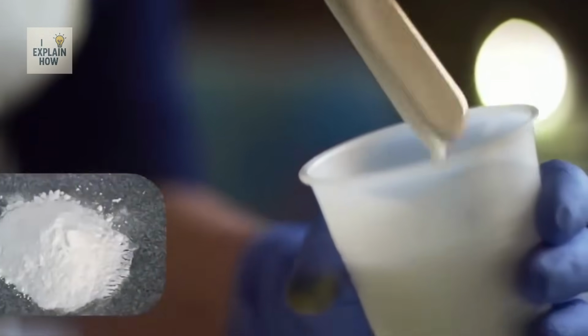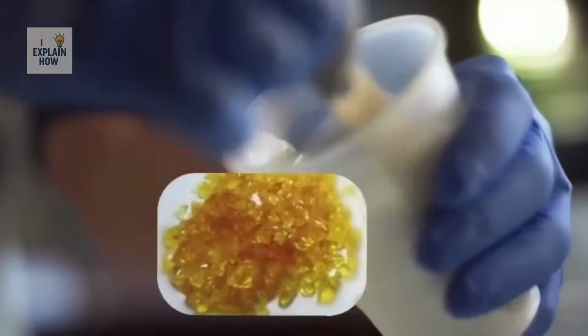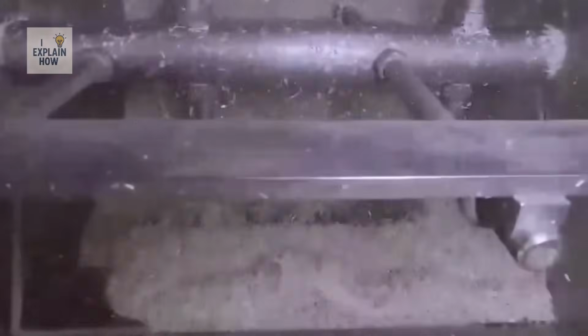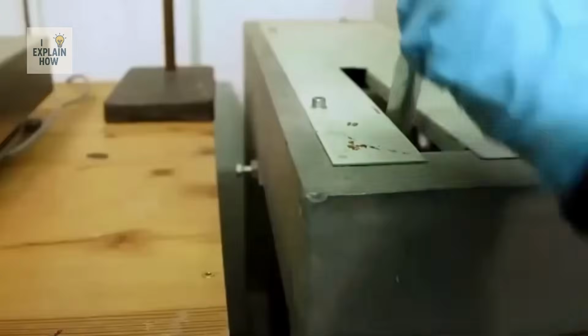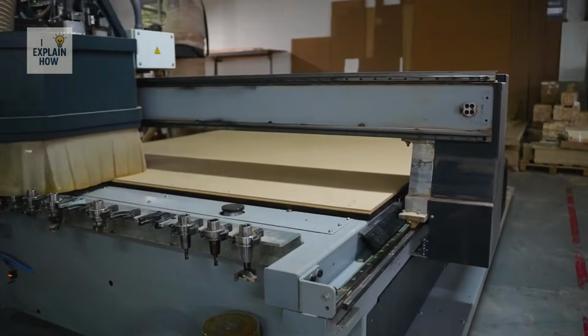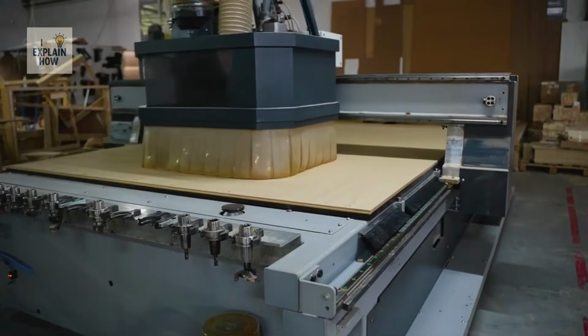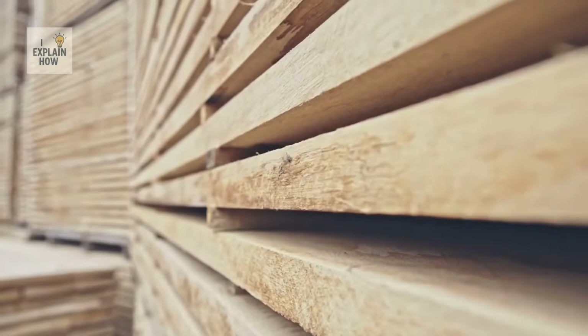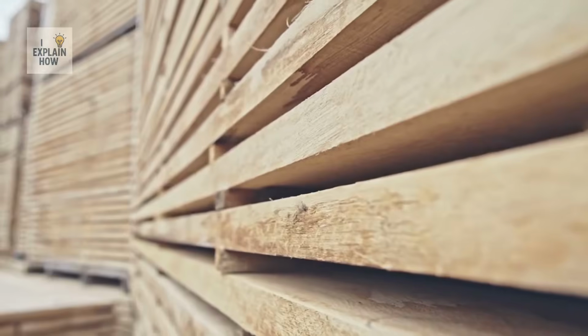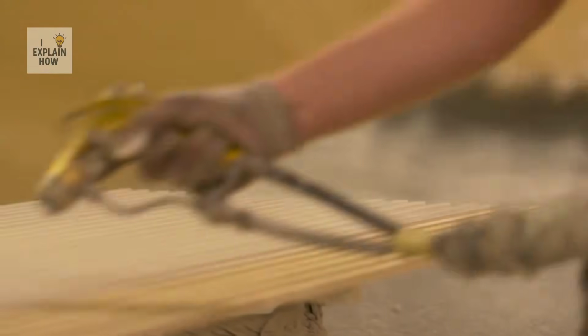This is where the binder comes in, mainly synthetic resins such as urea formaldehyde or melamine. The chips go into continuous mixers where the resin is sprayed in a sticky mist. Each particle is coated, ready to bond with the others. The quantity is crucial, varying between 6 and 10% of dry weight. Other additives can be added to improve strength or reduce flammability.